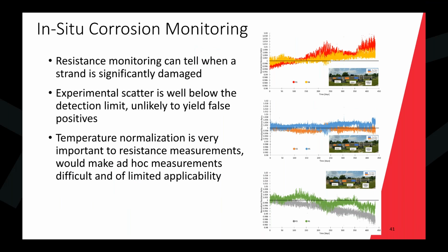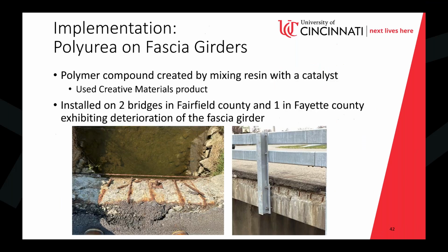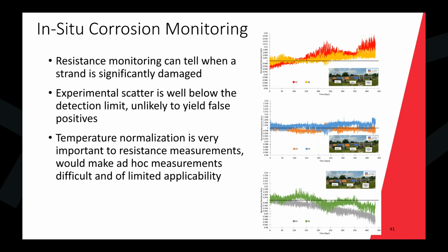And actually, through our other finding, because the steel is all interconnected, if one of the strands was completely corroded, it would still give you a measurement. You'd still be able to run current from one end of the beam to the other. It would just pass through the stirrups into another strand and then back to that strand past wherever the corrosion was. So negative findings are also important as to what we can and can't do in terms of monitoring systems here. And I believe that with that, I pass it back to Rachel, if there aren't any questions.